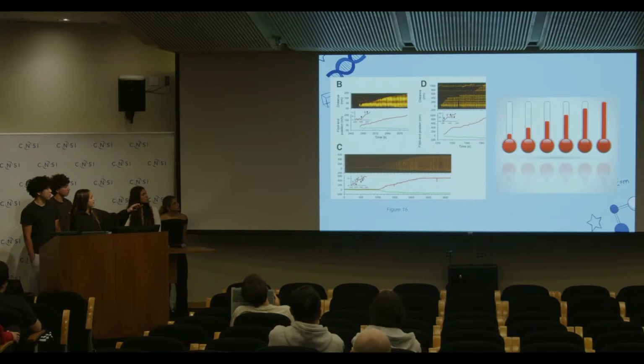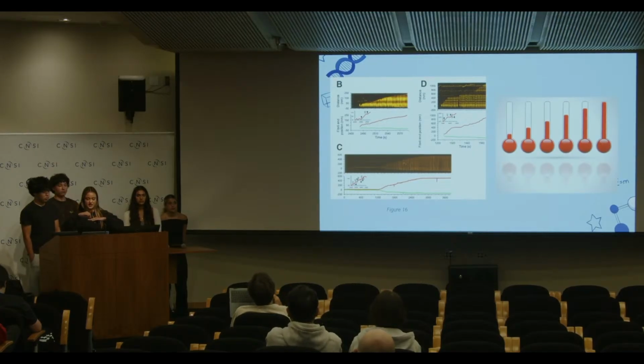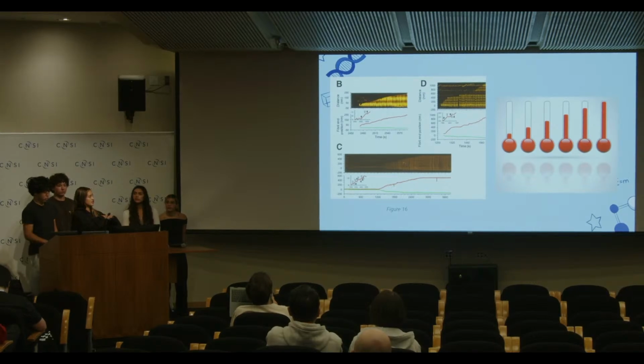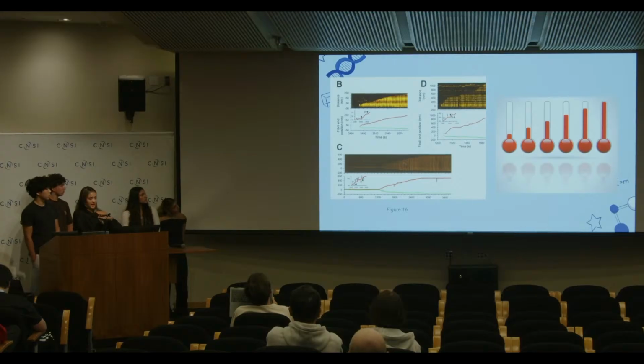That's kind of what we're looking at with the kymographs right here. Each of these little lines is a different image taken by the high-speed AFM of the amyloid beta protein. In AFM, when the probe is scanning the surface, as it moves higher up, the surface is going to be taller, and the contrast is going to be lighter. So the lighter sections right here are higher up, and that means the protein is more coiled. It's more spiral because there's more material.